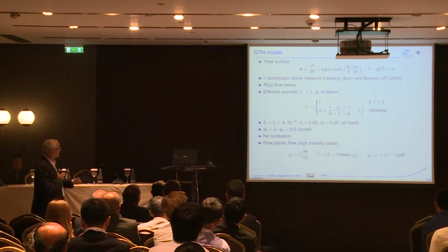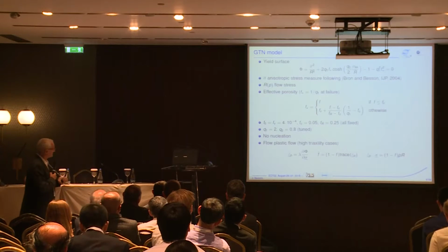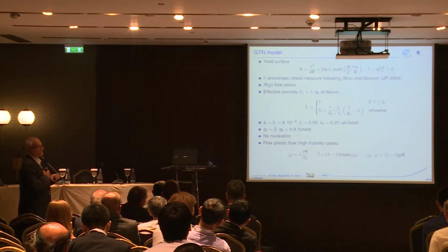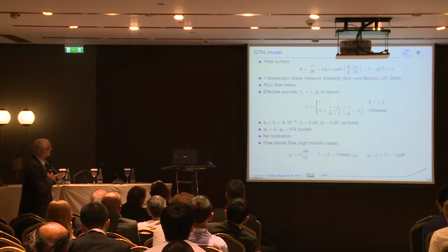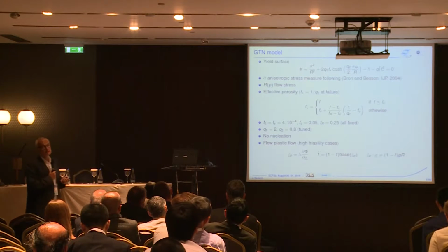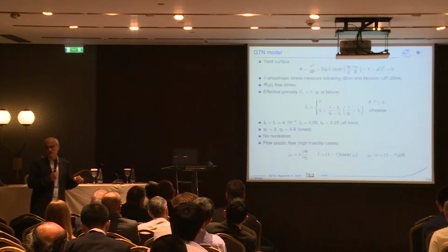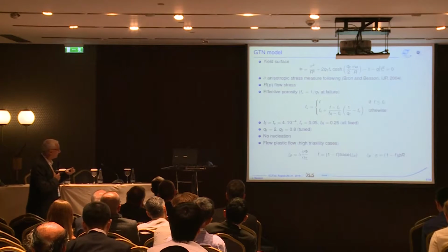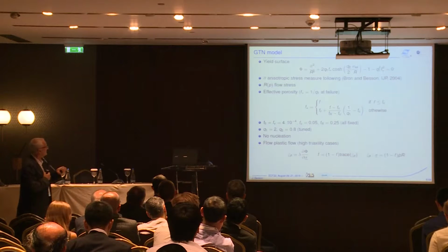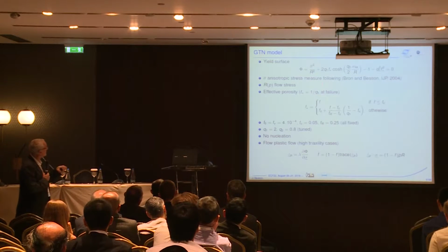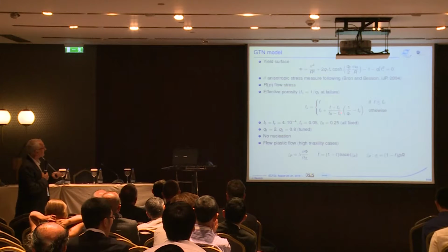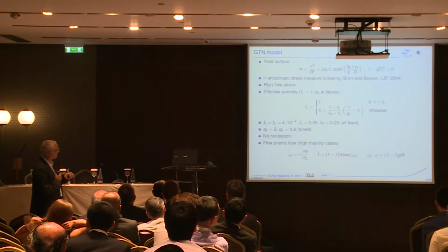And then we have to move to the damage model here. There was not a big effort done. We just used the standard GTN model. The only modification that we introduce is that here, instead of using the Mises stress, we use the anisotropic stress measure we have defined before. Otherwise, everything here is really following the standard GTN modeling, with the F star function for the description of coalescence and final failure.